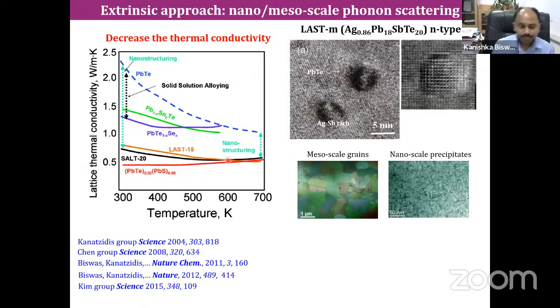Then several important papers came in this field. I have cited a few where people have created hierarchical architectures, from atomic scale point defects to nanoscale precipitates to mesoscale grain boundaries. So they scattered all ranges of phonons and got a ZT above 2 for the first time in lead telluride, and I was involved in that kind of work during my postdoc.